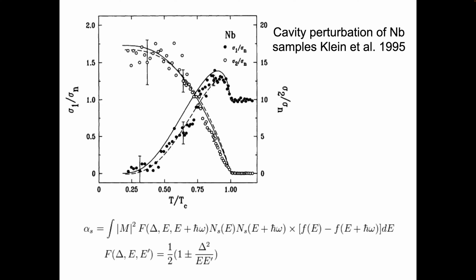And so this experiment, which was done really, really late, in 1995, surprisingly, the very first one, is kind of a microwave cavity version of the seminal experiment, which was done by Hebel and Slichter in the 50s. This idea of there being a resonance, some kind of increase in dissipation, comes up in other contexts. This is a little bit older school physics now, but 15 years ago, 20 years ago, people were very interested in the notion of the 41 meV peak in neutron scattering in a D-wave superconductor. And that's the same analogous phenomenon to this, but for the D-wave case.